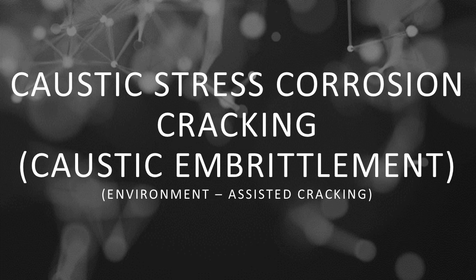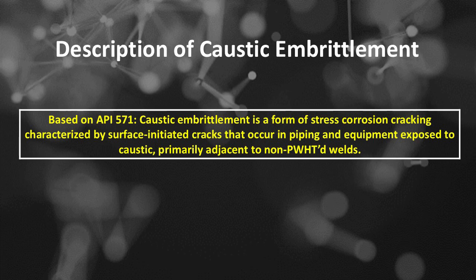Caustic stress corrosion cracking or caustic embrittlement damage mechanisms as a part of environment-assisted cracking. Description of caustic stress corrosion cracking or caustic embrittlement damage mechanisms based on API 571. A caustic embrittlement is a form of stress corrosion cracking characterized by surface-initiated cracks that occur in piping and equipment exposed to caustic, primarily adjacent to non-PWHT'd welds.